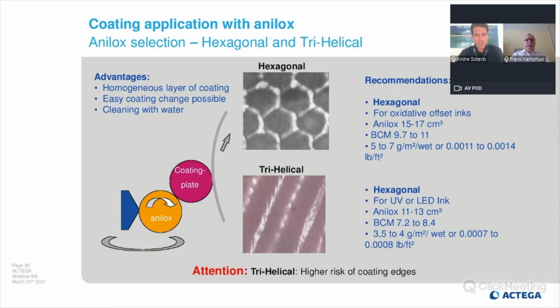The coating application is via an Anilox, so if you use the doctor chamber blade and Anilox roller, then you have a homogeneous layer of coating. You can easily change a coating and you can clean it with water. So you have your Anilox roller and apply it to a plate, and then it's applied to your substrates. And in principle, there are two different rollers on the market. That is a cell roller, like a hexagonal, or you have this line roller, the tri-helical Anilox roller.